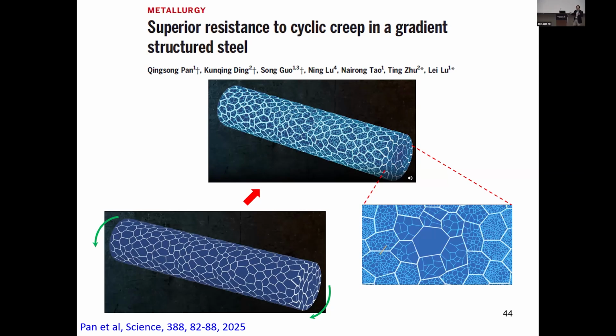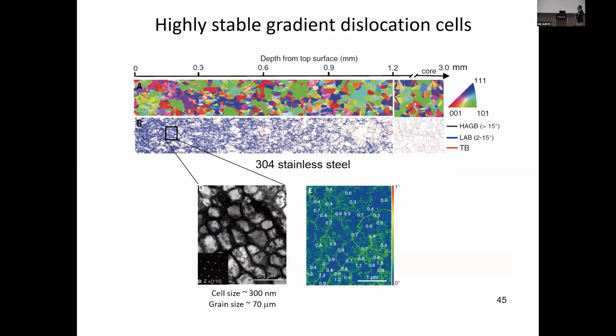In this case, it's not from the printing I introduced earlier. It's also different from the conventional method like severe plastic deformation. In this case, we just apply gentle and many small torsion cycles, and this enables us to produce the gradient dislocation cell structure with extreme stability. Then, as we apply the further cyclic tension compression load, this produces very good resistance to the ratcheting or the cyclic creep.